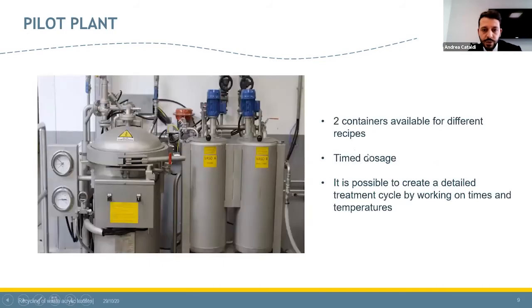It is also possible to consider 2 containers available for different recipes. So in container A, it's possible to put one recipe before starting, and in container B it's possible to put another recipe. So during the cycle, it's possible to dose chemicals at different times, and it's possible to create a detailed treatment cycle by working on times and temperature.